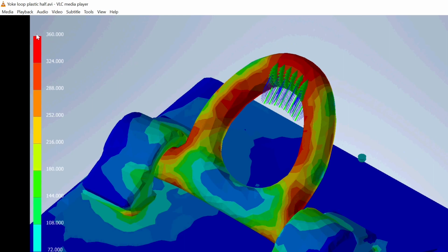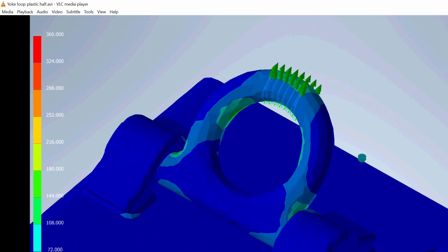This red area has stresses above 360, which is the limit, and then that produces a risk of pull through, so the attachment might get disconnected by causing this area to fail and just sliding out once it opens up. This area then also is at some risk of failure because there's a full area being loaded near the extremes, but in the simulation that's holding, so that might actually hold the design load, and so forth.